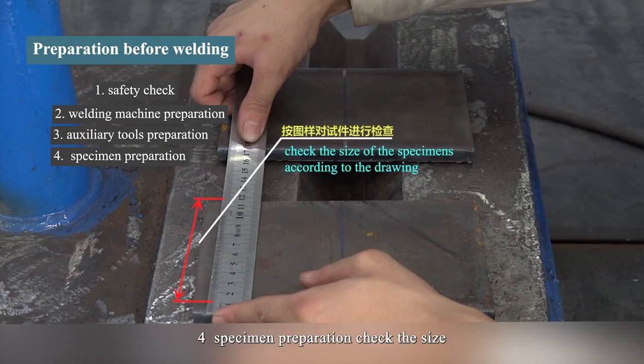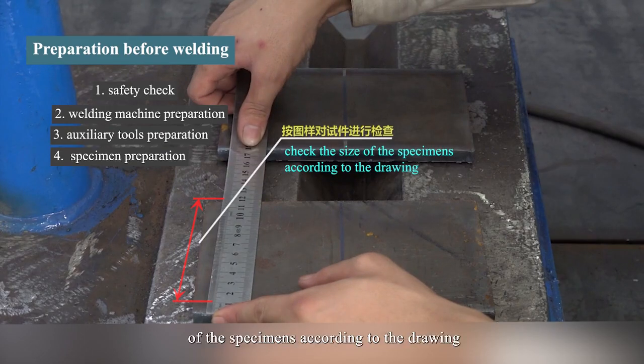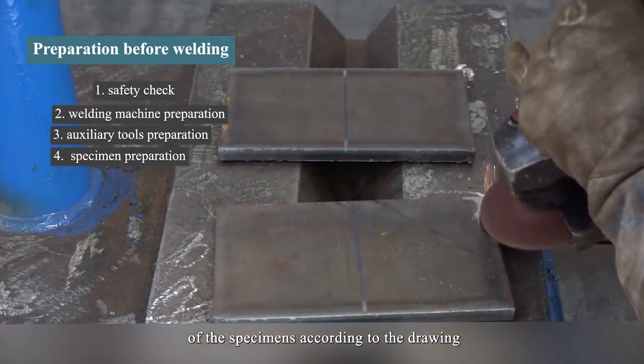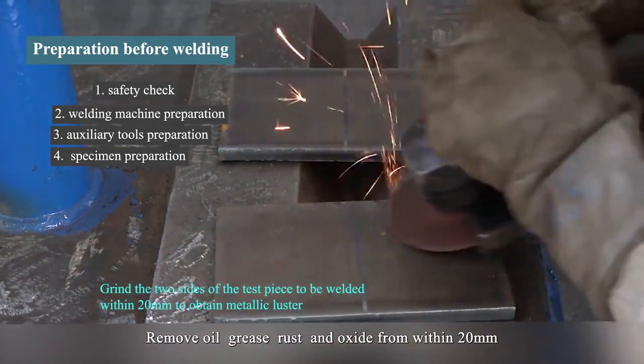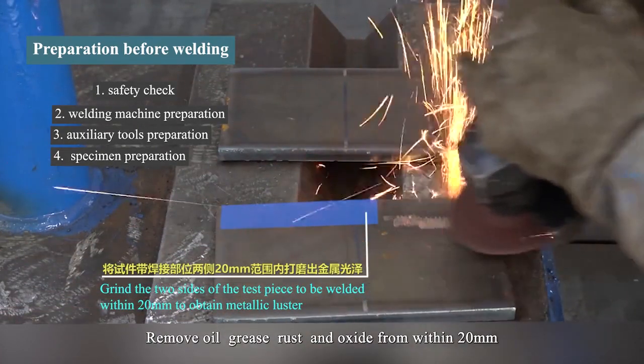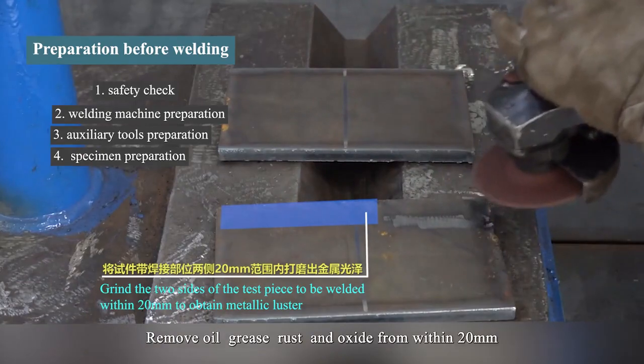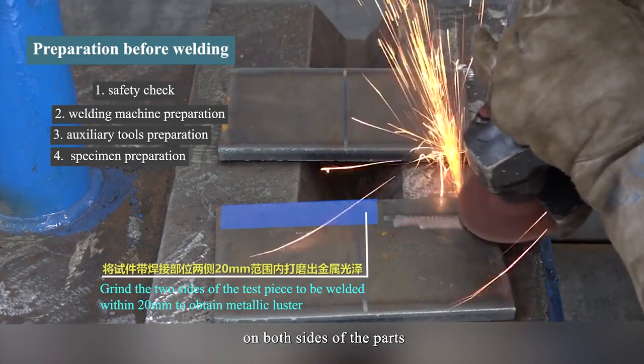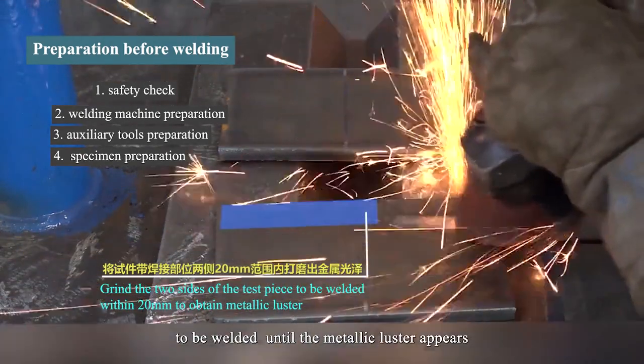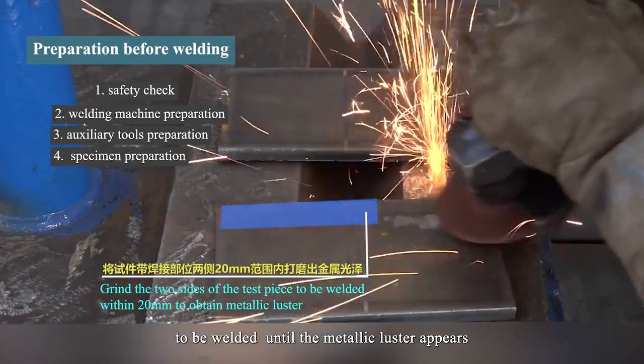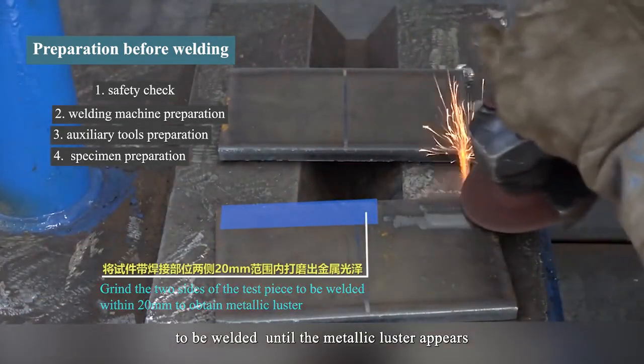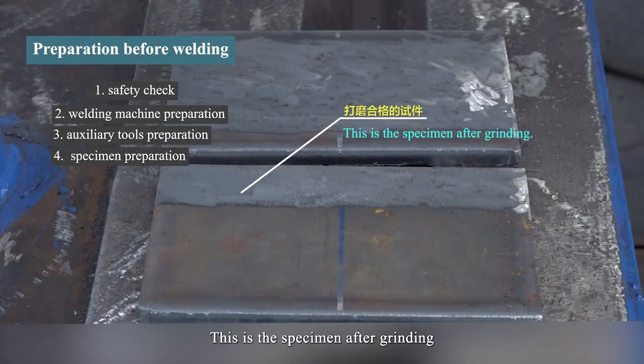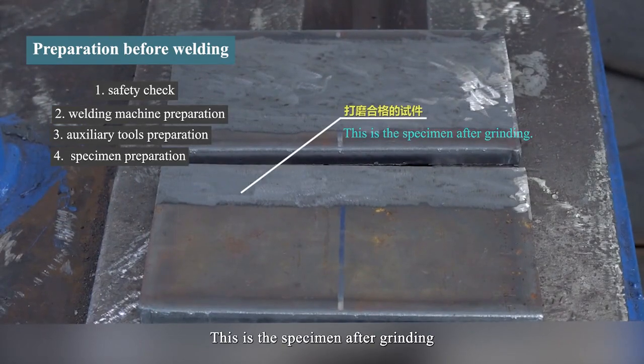Fourth, specimen preparation. Check the size of the specimens according to the drawing. Remove oil, grease, rust, and oxide from within 20 mm on both sides of the parts to be welded until the metallic luster appears. This is the specimen after grinding.